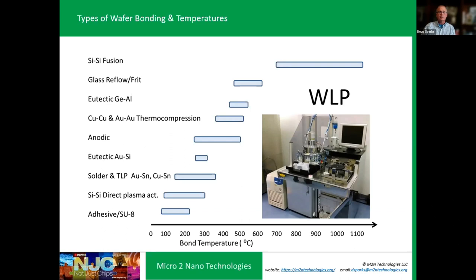And of course, there are things like silicon direct plasma activation bond, which is essentially room temperature. Maybe you'll do an anneal at 150. And then you can do SU8 and other adhesive bonding for extremely low temperature devices, say infrared devices that may have some low temperature film on the exterior of the lens. So again, the application and the material set will determine what wafer level packaging strategy and process you'll use.